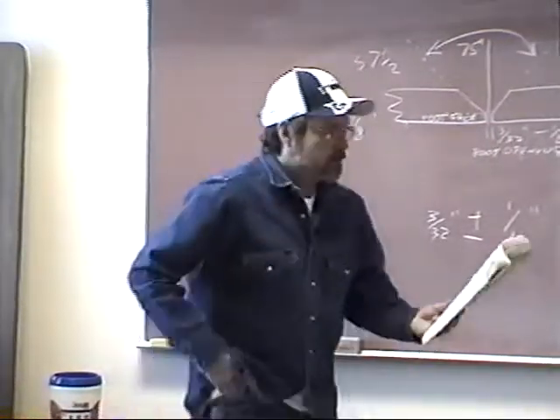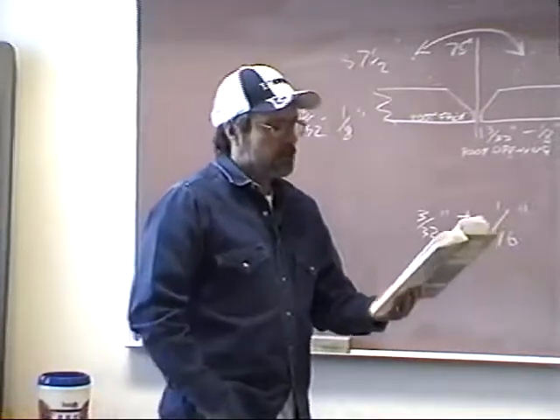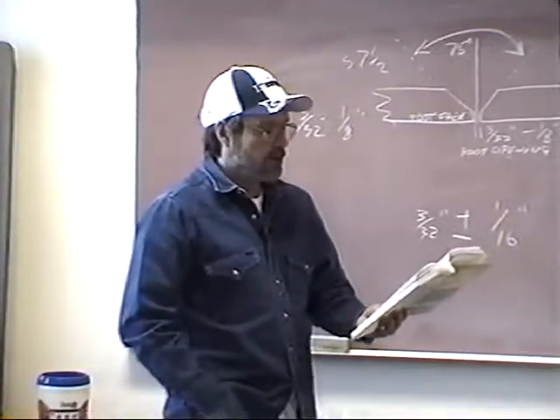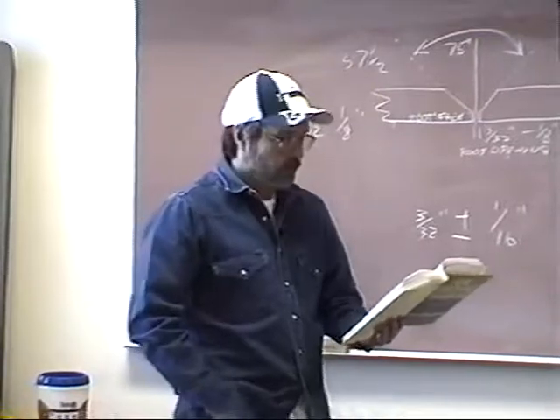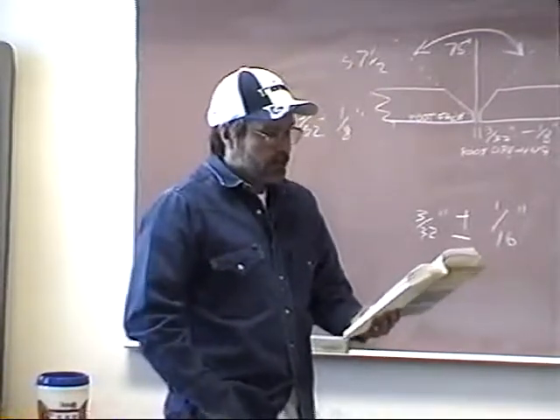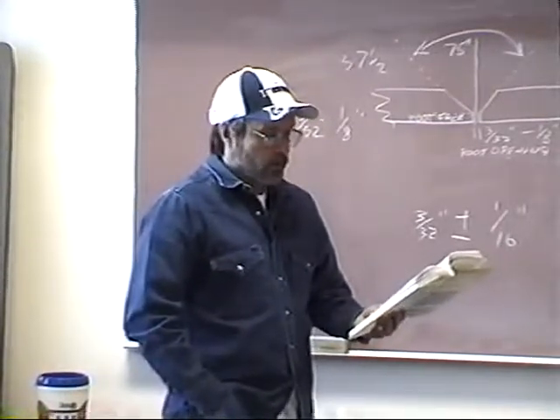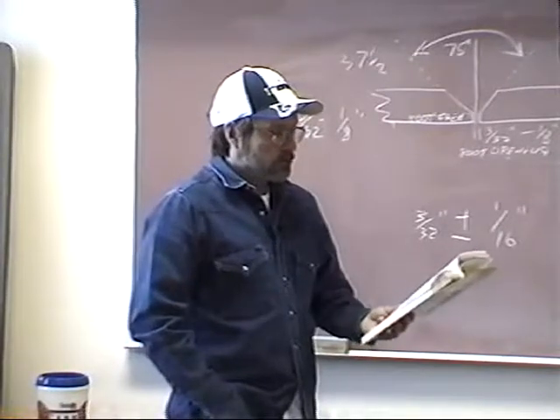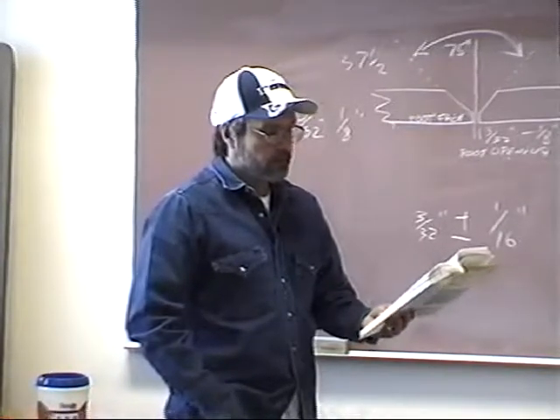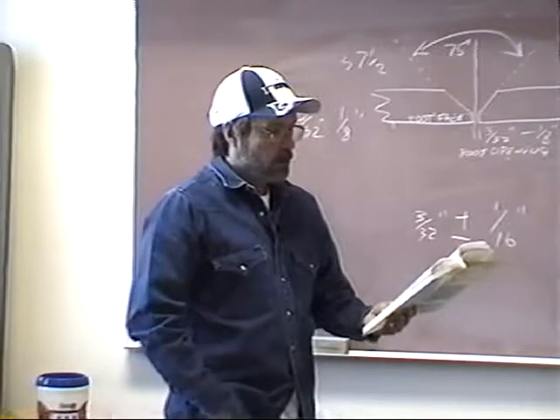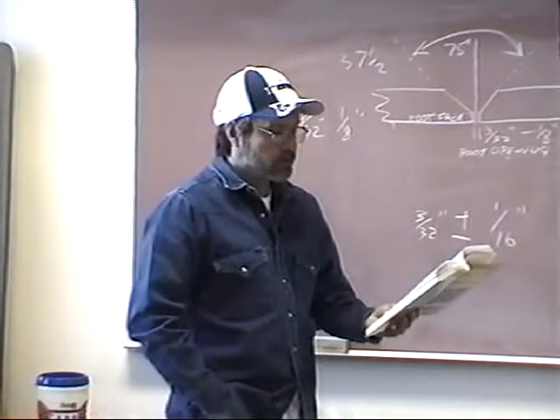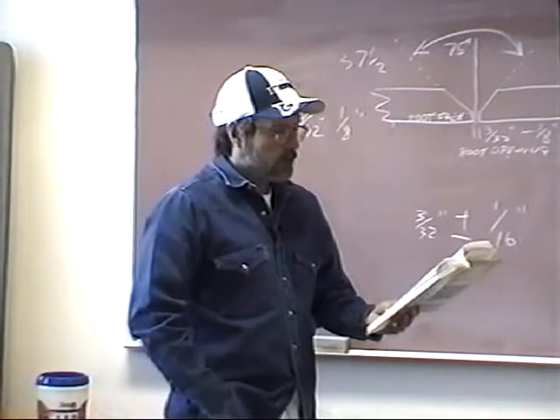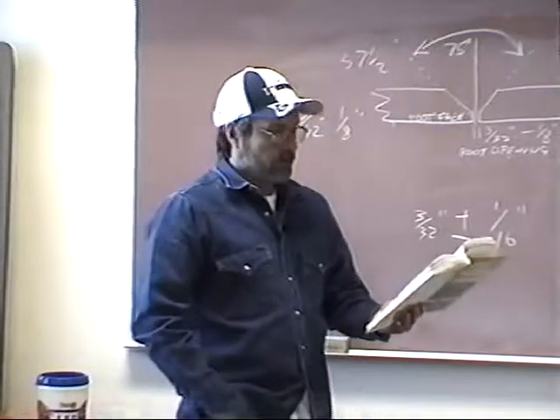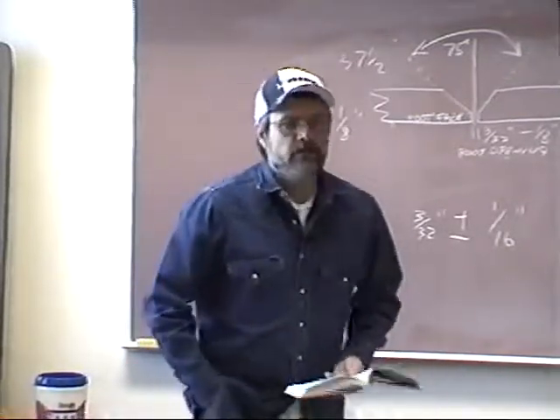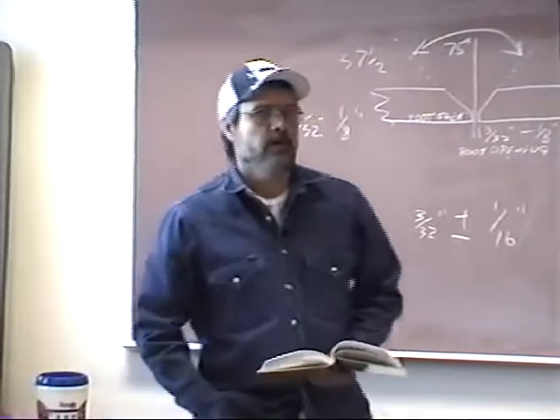Reading on the next page, it says, the surface produced by the oxyacetylene cutting torch will have a tightly adhering oxide film. If not removed, this film is very detrimental to the quality of the weld. For this reason, the beveled surface should be entirely free of the film before any welding is done over it. The oxyacetylene cutting torch also produces a rather rough surface that is difficult to weld over, so you want to make sure you smooth it out. If you're using a beveling machine, it's really not that bad. They really come out pretty nice.